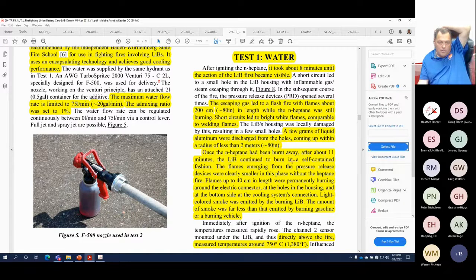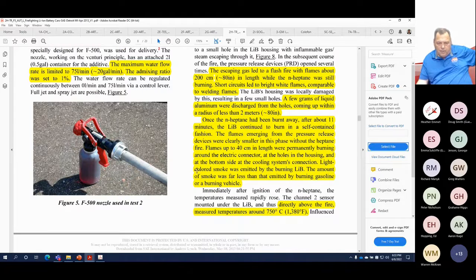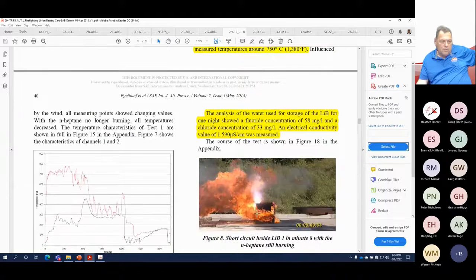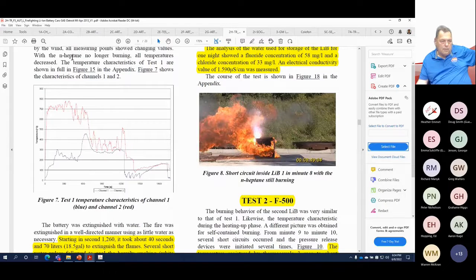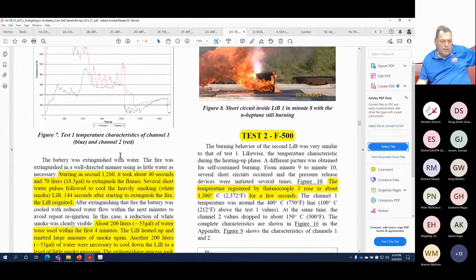After 11 minutes, it continued to burn in a self-contained fashion. The flames emerging from the pressure release devices were clearly smaller in this phase without the heptane. Flames were up to 40 centimeters high. So it just talks about it directly above the fire. The temperature was 750 degrees C. So here they're showing 750 degrees C.